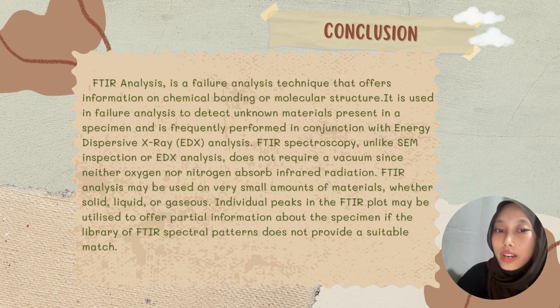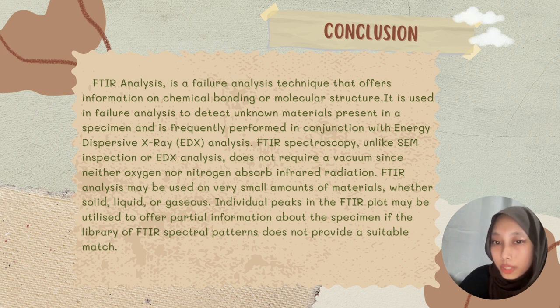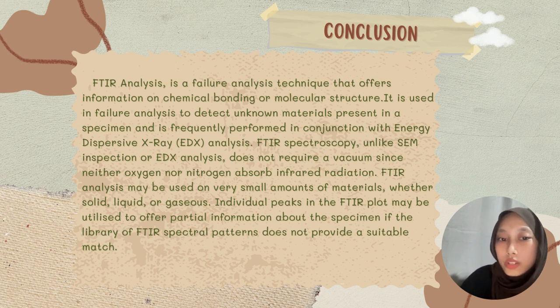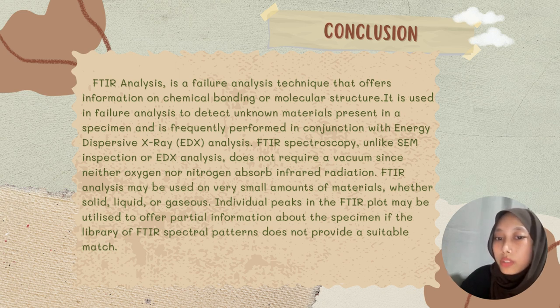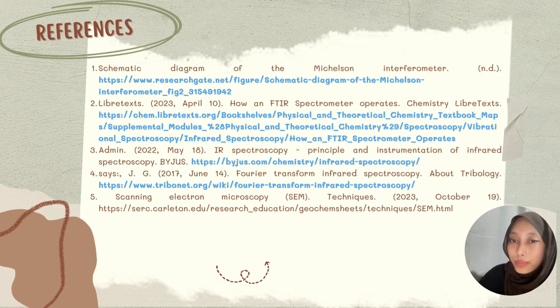In conclusion, FTIR analysis is a failure analysis technique that offers information on chemical bonding or molecular structure. It is used in failure analysis to detect unknown materials present in a specimen and is frequently performed in conjunction with energy dispersive X-ray (EDX) analysis. FTIR spectroscopy does not require a vacuum, since neither oxygen nor nitrogen absorb infrared radiation. FTIR analysis may be used on very small amounts of material whether solid, liquid, or gas. Individual peaks in the FTIR spectrum may be utilized to offer partial information about the specimen if the library of FTIR spectral patterns does not provide a suitable match. Thank you for watching.